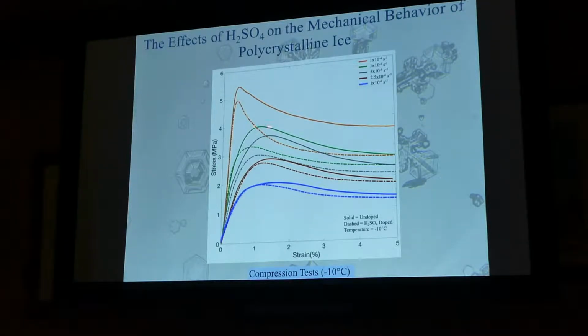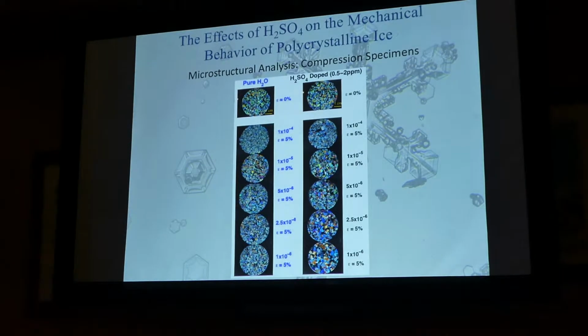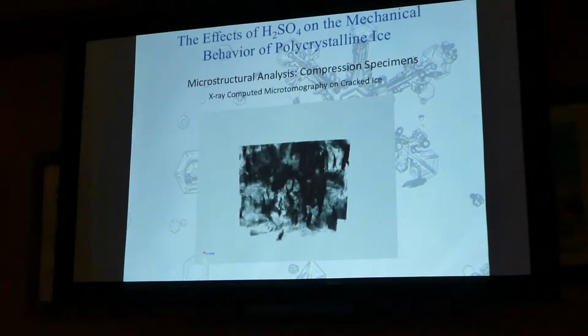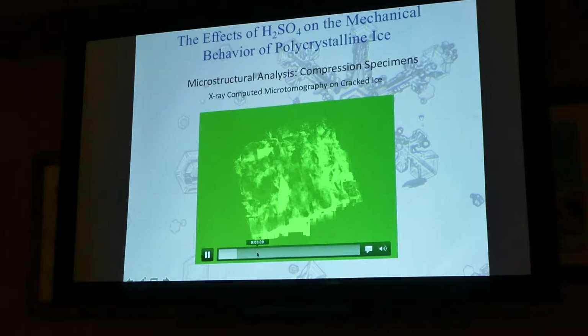And we saw that consistently at all these different strain rates, even though they started to come together a little bit more down here. And that's more related to some fractured more than others. So in general, just a little bit of sulfuric acid in the ice weakened it. We also saw differences in the microstructure. So here we saw, for instance, larger grains that came out at the end of the test than over here. That was something that we saw in all of our samples. And we also were able to do some micro CT analysis on these compression tested samples to see how many cracks had formed, or where the cracks had formed in the ice.